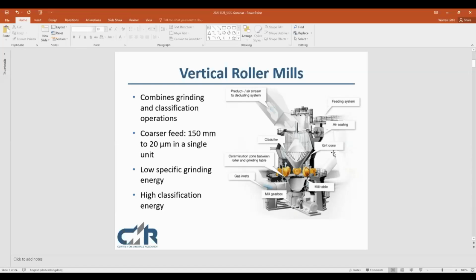At least in airflow applications, we have a dynamic air classifier, which is the top part here, situated above the grinding components. And this is where the classification happens. These devices, the largest devices, can receive top size feeds of up to 150 millimeters, and in a single unit, take the P80 down to 20 microns. So quite a large size reduction there in a single unit.